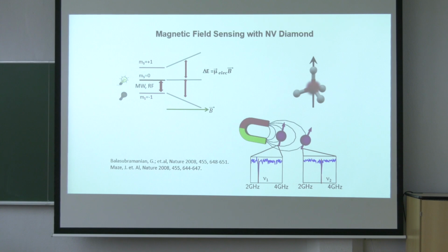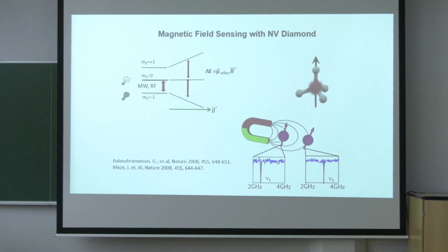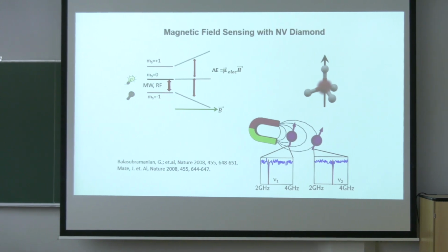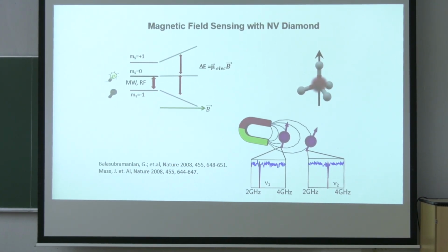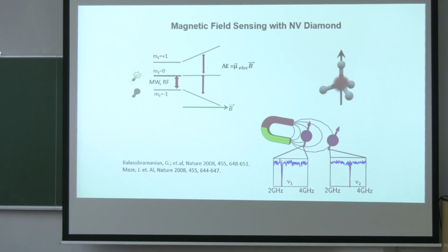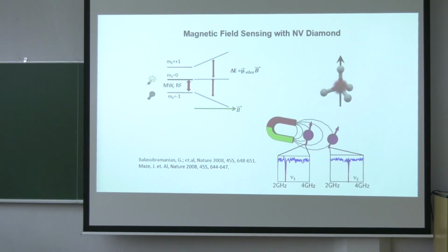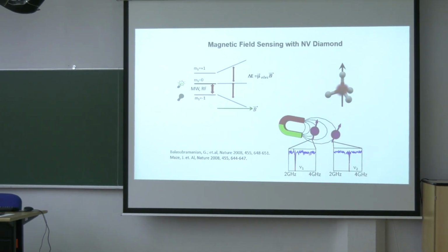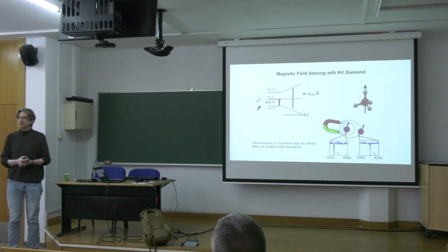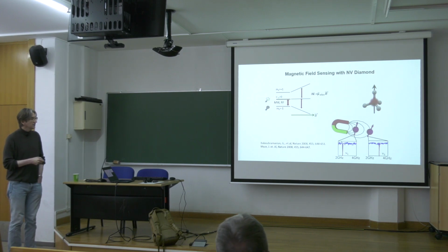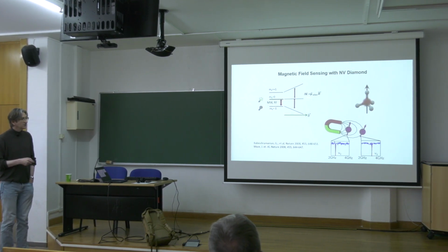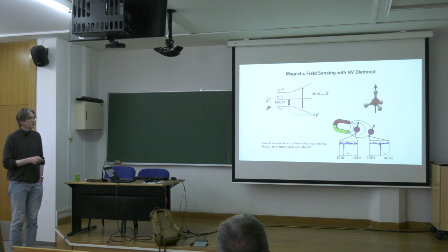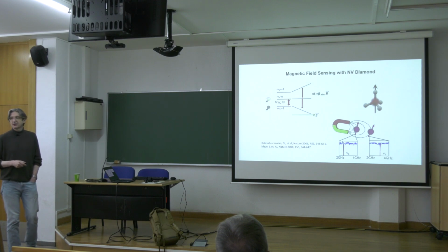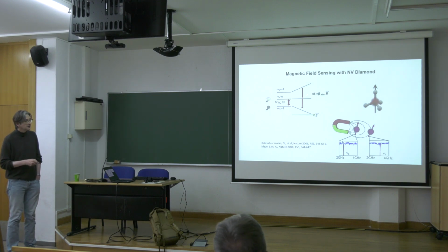I will start with converting a qubit to a magnetometer. For a qubit, usually you like to have a very long coherence time, but also not to be very sensitive to external perturbation. But spins are intrinsically coupled to a magnetic field. For a spin half system, you have Zeeman splitting. The same is true for the spin 1 system, which is the NV center. So if you apply a magnetic field, one of the sublevels is not reacting to the field because its magnetic quantum number is 0, but the two others are getting split. And if you measure the splitting, it's related to the magnetic moment of a single electron, which is very well defined. So by measuring the frequency splitting, you can measure the magnetic field.